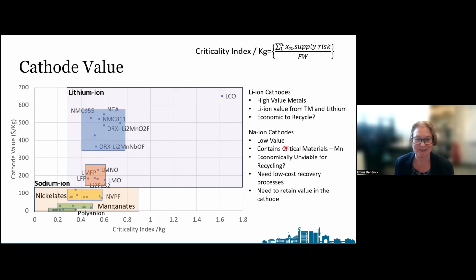We could do a quick assessment, and I just wanted to highlight some of the value against the criticality between different cathode materials from different types of technology. So I've got lithium cathodes here, and then sodium ion on the bottom. And as you can imagine, just because we're substituting lithium for sodium, actually the value of these materials reduces significantly, because lithium is a relatively high cost material. And also reducing the content of lithium improves the criticality in some cases, but not all cases, because we're still using nickel and manganese in some of these materials.